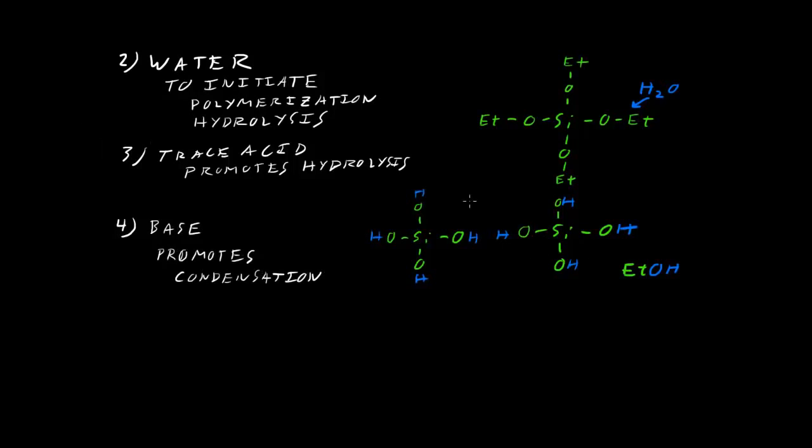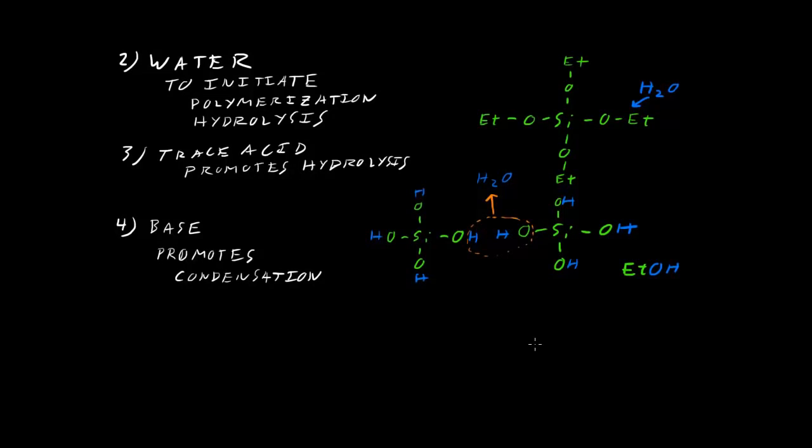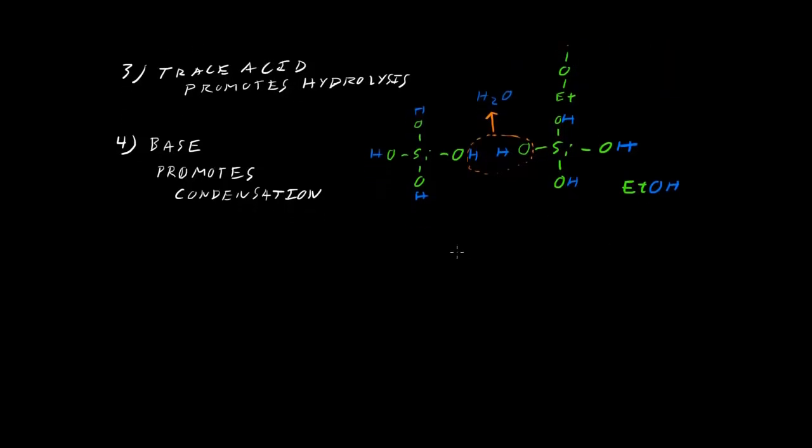So the base will actually allow these adjacent hydroxyl groups to bond with each other and form water. So now the water gets kicked off and floats off into the distance, and if you look at what is left, we have our silicon and oxygen and a silicon bonded together.